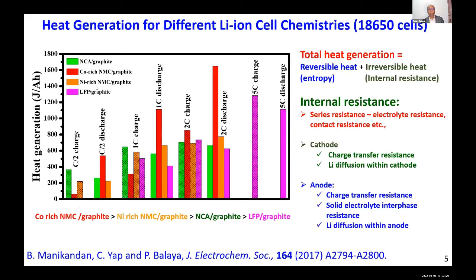This is yet another example. I have taken the same 4 chemistries which I introduced previously: NCA graphite, cobalt-rich NMC versus graphite, nickel-rich NMC versus graphite, LFP. And then if I look at charge-discharge, this is 2-hour charge, 2-hour discharge, or here 2C discharge, which means 30 minutes discharge. You can clearly see LFP graphite is the one which has low heat generation. This is actually joule per ampere hour, normalized to ampere hour, because all these chemistries have different ampere hours. So we are normalizing it to per ampere hour.